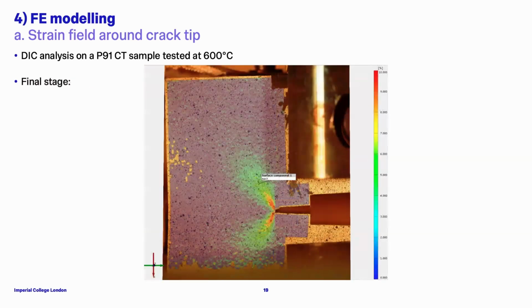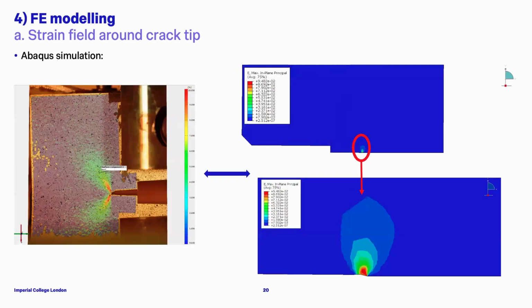Finally, I did some DIC analysis on a sample. Here is the strain field at the very end of the test on a P91 at 600 degrees. What we can see is in good agreement with what we could expect. That is to say, the highest strain values are around the crack tip. I checked it with an Abaqus simulation, also using the same material properties, and they give almost the same maximum value, around 10%. So it is in good agreement.